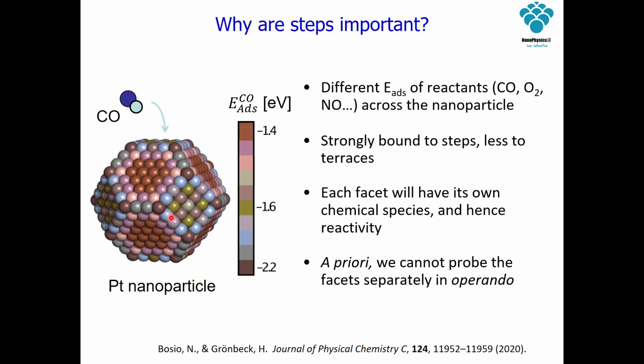If we have another terrace, so this is, let's say, a 111 surface, this would be a 100 surface, then you see in the middle of the terrace we have another energy for this CO adsorption. And if we go, for example, to these corner atoms over here, then you see CO would stick very strongly to these corner atoms and would be bonded quite a lot. So now we can make such a calculation, but this will not help us yet to know where actually our process will happen, our CO oxidation.